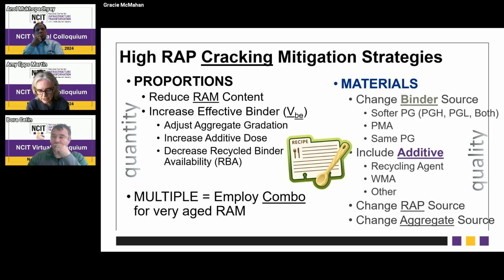And another thing that an agency could do is to decrease the amount of credit given to the RAP binder. So we can decrease the amount of recycled binder that's available, because that's probably a real thing. Probably between 60 and 85% of that RAP binder is available, and the rest of it is not. The last thing we can do is reduce how much RAP we're putting in there. Maybe in some cases, if it's very stiff RAP, we can't go up to 50% RAP. We can only go to 30%, for example. And sometimes if we have very aged RAP, we have to employ a combination of these strategies. Next slide, please.